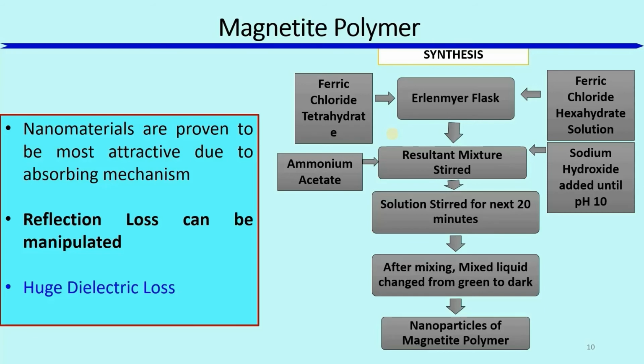Magnetite polymer is prepared by mixing ferric chloride tetrahydrate and ferric chloride hexahydrate solution with mechanical agitation at 80 degrees Celsius in a flask. In the resultant mixture, sodium hydroxide and ammonium acetate are added until the pH level increases to 10. After mixing, the solution is stirred for the next 20 minutes.